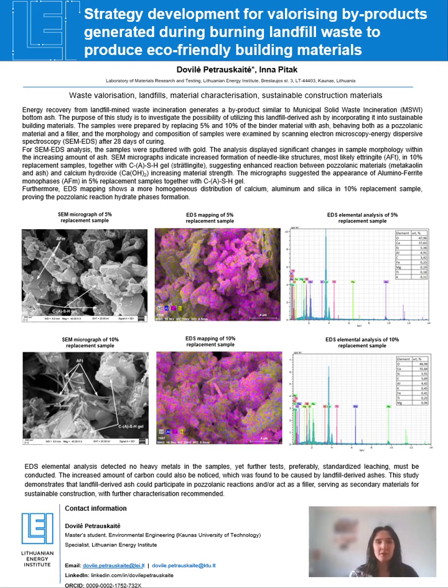So for this work, I prepared samples where 5% and 10% of the binder was replaced by landfill-derived ash, and the binder system itself contained metakaolin and calcium hydroxide. So after 28 days of curing, the samples were sputtered with gold to make them conductive, and then analyzed using scanning electron microscopy coupled with energy dispersive spectroscopy.